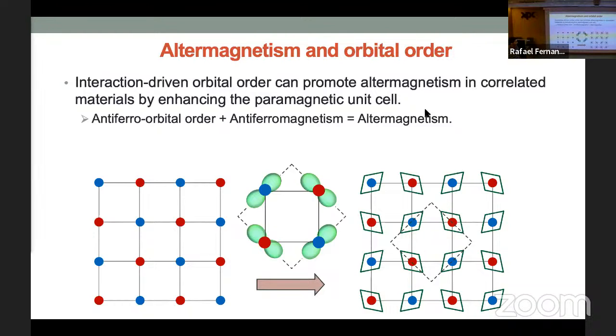This case would be an antiferro orbital order, where you see, for example, some atoms have xz plus yz, and this one xz minus yz, and this is equivalent to this situation. In fact, that's a way where you can get structural distortions as well, right? And so the key point here is that if you combine antiferro orbital order with antiferromagnetism, you can get an altermagnet.